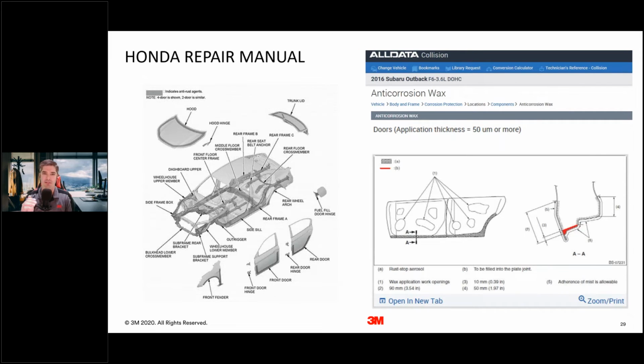And say like the top of a rocker panel, is there enough on my weld up here to protect it from any moisture that might get into that cavity and start rusting the backside of that panel? With our cavity wax, we actually have a foaming action designed and built into it. So when you use a straw or a wand for it, it foams up upon application, but then that foaminess subsides. And when it subsides, it accelerates the wicking action even faster.